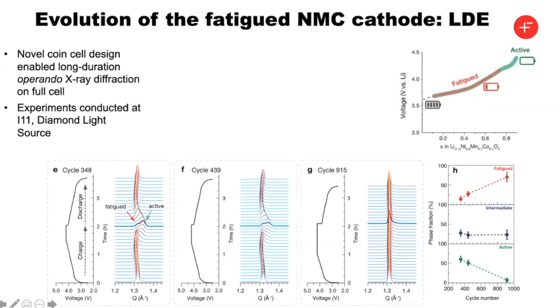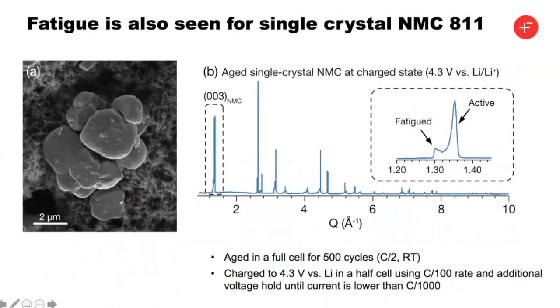So this is just summarizing what we're seeing. The fatigued phase is essentially getting to 4.2 volts and it doesn't continue any further along this higher voltage process, which is then associated with the collapse of the C parameter. So we then started to think about what was going on in the system. One of the questions we had was associated with cracking between the primary particles and the large secondary particles of the more traditional 811s.